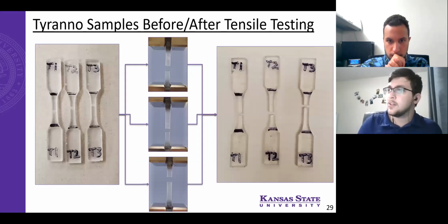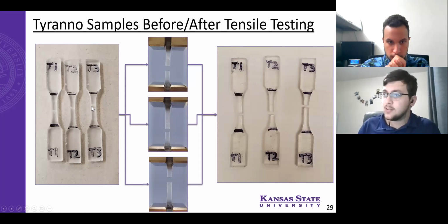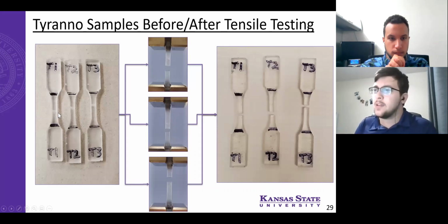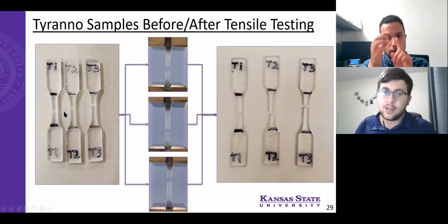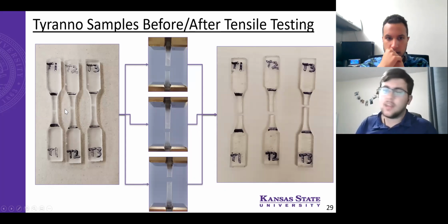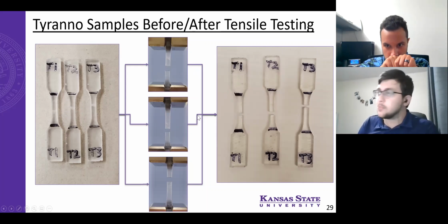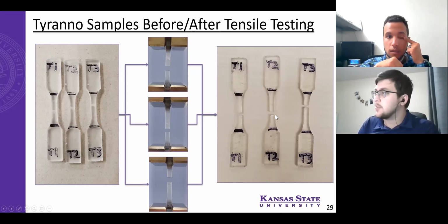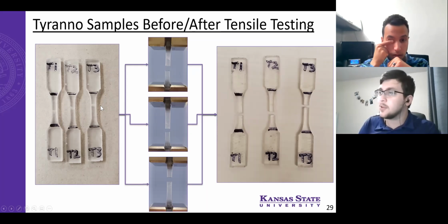So moving on to the Tyrano samples, again before, during, and after fracture. I'd like to note you can see these little lines here where I measured the samples with a digital caliper, which I believe may have influenced where these broke, as well as how they broke and how soon they broke. Does it press on it too much? Yeah, I think I just pressed them too hard when I was trying to measure it. Okay. And is that the location where it broke? Yeah, you can see, so this is the first one. That's pretty close to where that was. The second one is not so much, but the third one definitely looks like it broke in about the same spot.